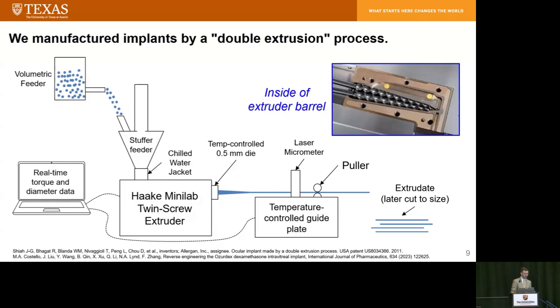Moving on to manufacturing. We manufacture these implants by a double extrusion process. We developed this process based on the Ozurdex patent as well as our general knowledge of extrusion. And ultimately, the process that we developed worked very, very well. Basically, the process is to feed the blend of the drug and PLGA powders into a twin screw extruder. So this photo shows what the inside of the extruder looks like.